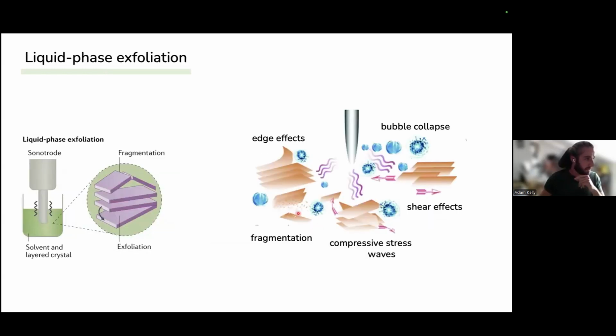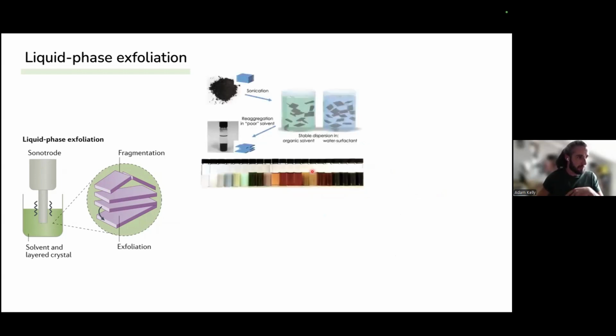So just a quick recap on what liquid phase exfoliation is. We take a sonic tip or a sonic probe, we put it into a solvent that contains our layered crystal, and we excite this here, and this applies sonic energy into this dispersion. And the vibration frequency of this probe, it creates bubbles and cavitation, and as the bubbles collapse, they transfer stresses to the material inside in the solvent. So this creates shear effects, it creates compressive waves, we get fragmentation of our nanosheets, so they begin to shatter, and also edge effects cause peeling. So what happens here is you're delaminating, you're breaking up the crystal, and this allows you to generate nanosheets.